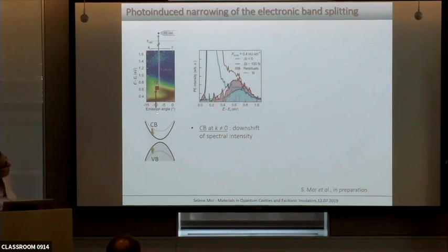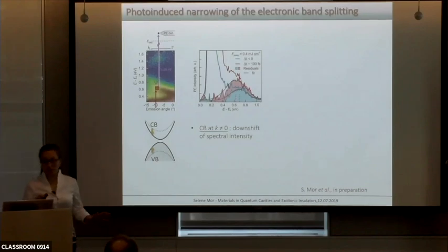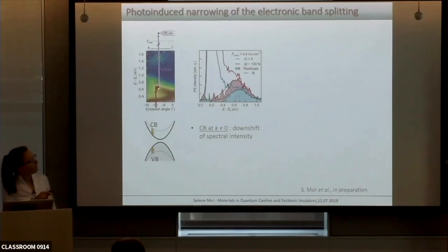And I can show you the data. What you see here, for example, at the very lowest intensity, this big peak, is already inelastically scattered electrons, which have no relationship with any bands, and it's just background. My point is the following, maybe I'm completely naive. You have to do a transition with 1.5 eV, which is way below the bottom of the conduction band. Then this has to relax. And in all those processes, with the next photoelectron, you can excite from both the top of the valence band or the bottom of the conduction band. The top of the valence band you will never be able to photoemit, because if there is no excitonic insulator, you do.